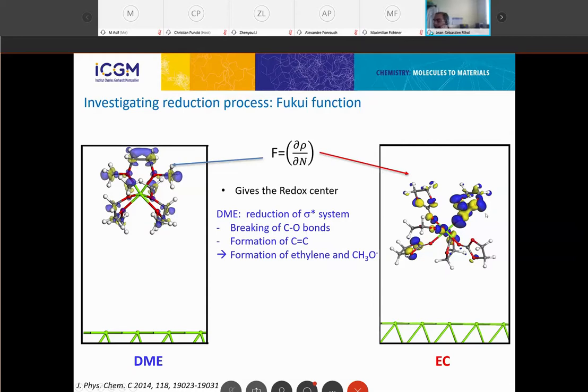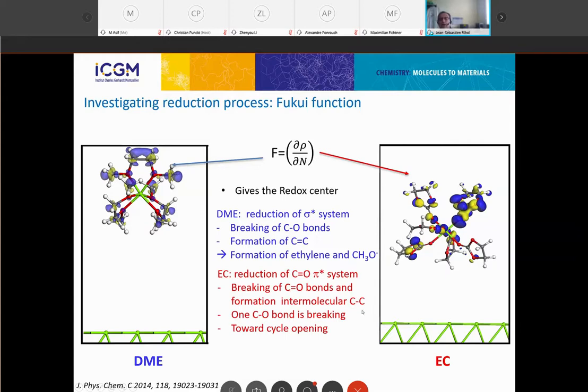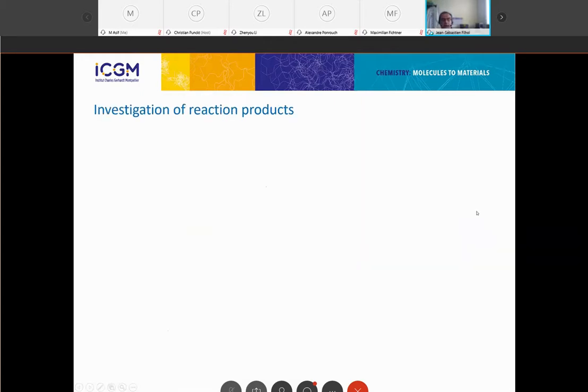While for the ethylene carbonate, what's going to happen is a reduction of the pi star bond. And we also see that we are going to weaken a lot, because we are going into an antibonding space, the CO bond in the ring. So that means in this case, we are going to favor the dimerization, but we are going also to favor the ring opening in ethylene carbonates.